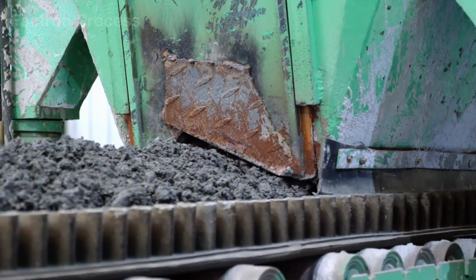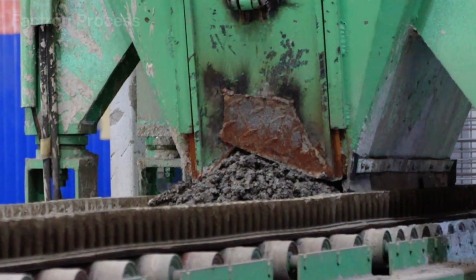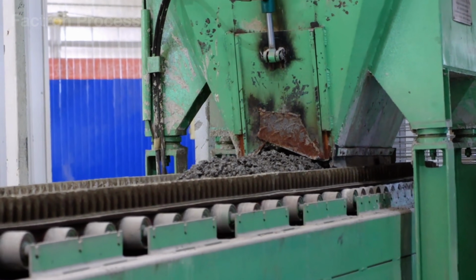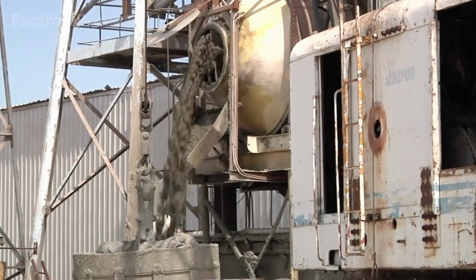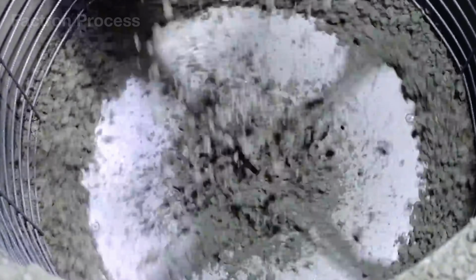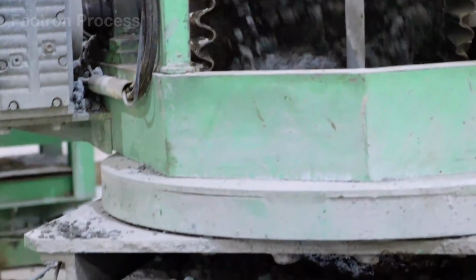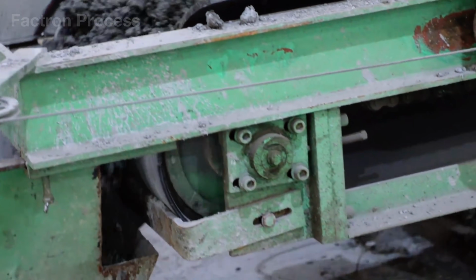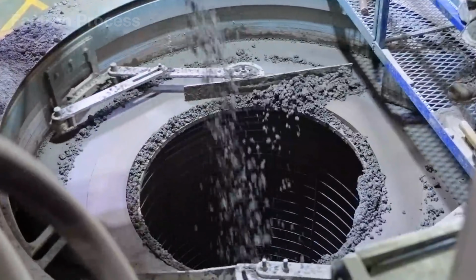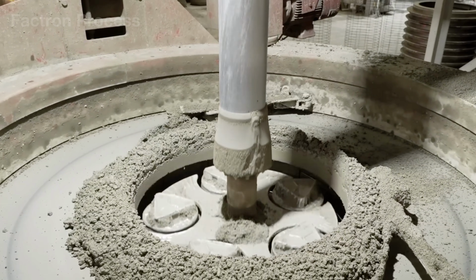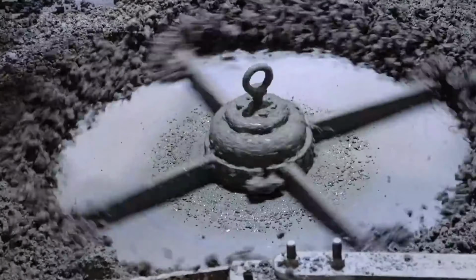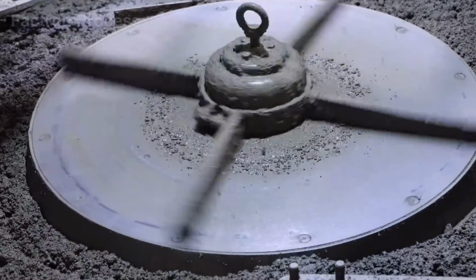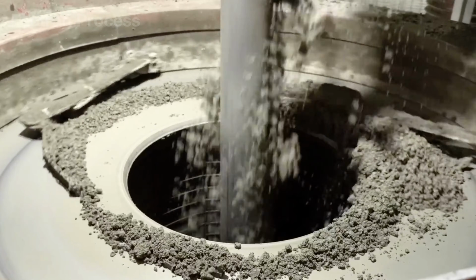When the mold has been tightly locked, dry concrete from the mixer begins pouring from the hopper into the space around the reinforcement cage. This mixture almost does not flow on its own, so the steel distributing blades above must rotate continuously, sweeping the concrete into an even ring instead of allowing it to pile up in clumps. Just below, the packer head begins forming the pipe wall. Its rollers spin with force, pushing the concrete outward, pressing the mixture tightly against the steel mold and compacting it around the reinforcement cage.